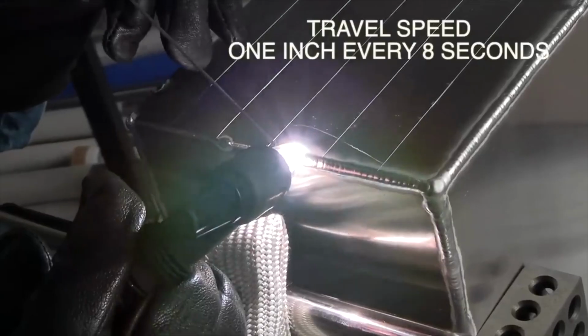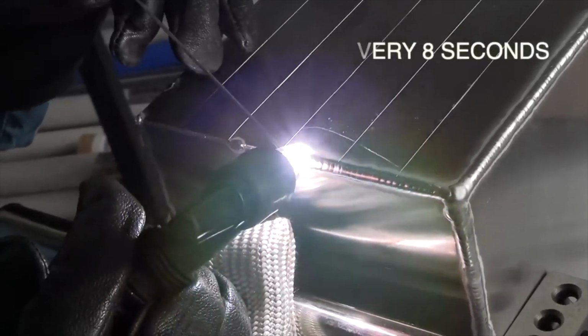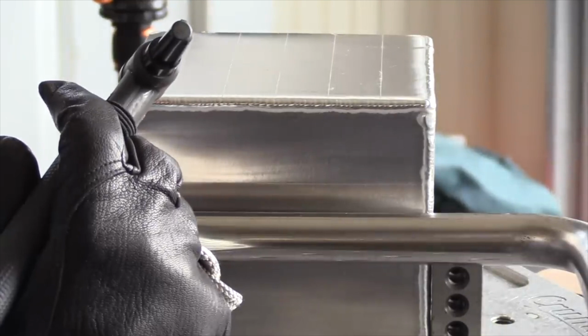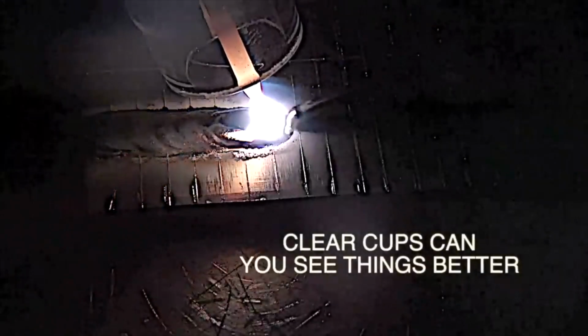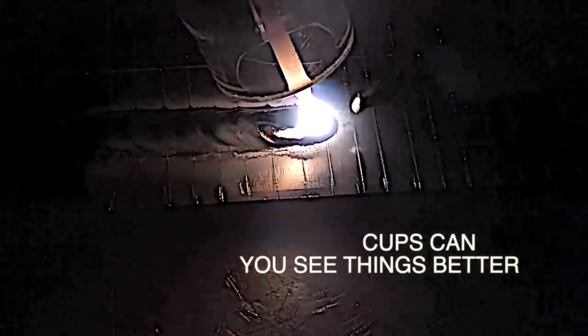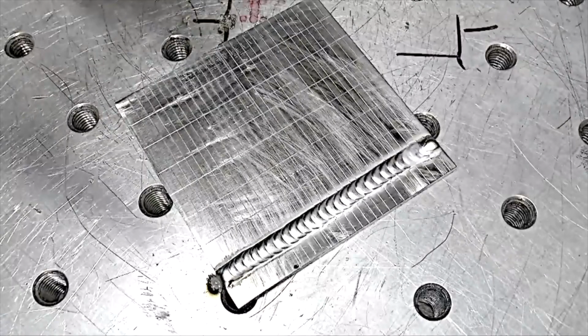For thicker aluminum, I often move the torch ahead about 1/8 of an inch between dabs of filler wire. But for thinner aluminum, if you move ahead too far, you can blow a hole. When I first saw a clear cup at a FabTech, I was kind of skeptical. I didn't use them for years, but then when I first tried one, just trying to film a good arc, because I knew it would light everything up, I discovered really quickly it helps me see better.